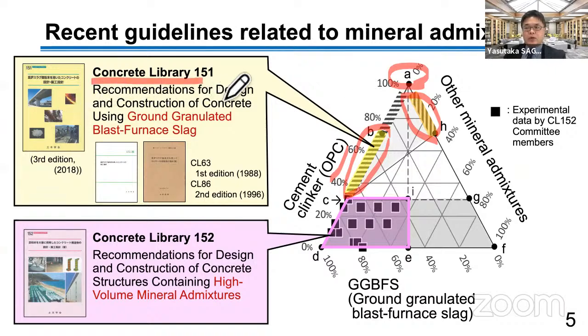The title of Concrete Library 151 is Recommendations for Design and Construction of Concrete Using Ground Granulated Blast Furnace Slag. Slag cement in Japan has over 100 years of history. In JSCE, the first guideline of slag cement concrete was published in 1988. The second edition was published in 1996. So the current version is this one, Concrete Library 151. The target of this guideline is slag cement class B and class C and equivalent level. So you can mix the blast furnace slag in the mixing plant.